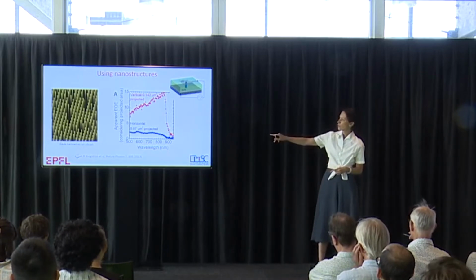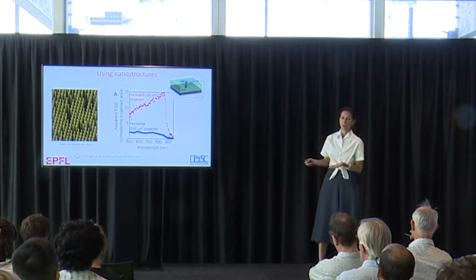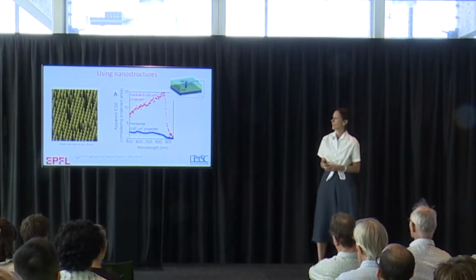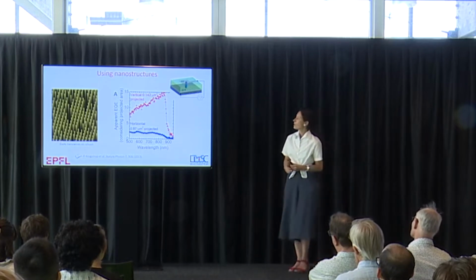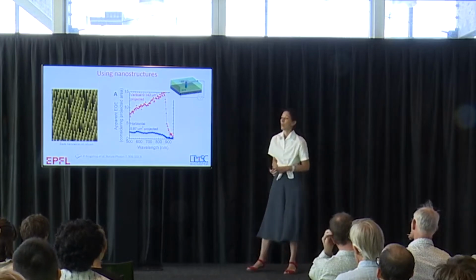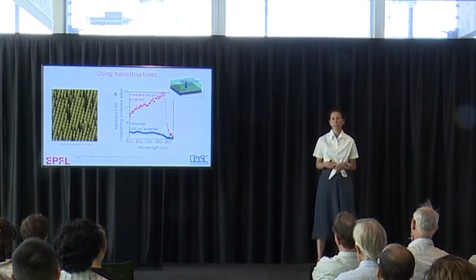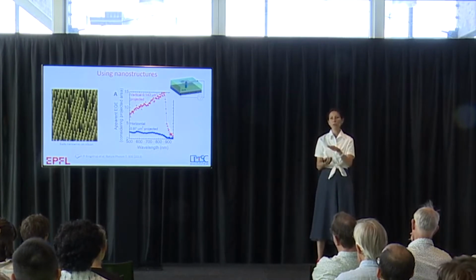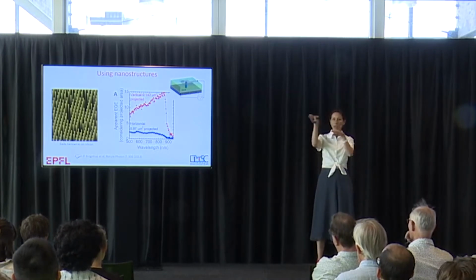As we didn't know how to do this, but we were able to get some wires grown on silicon vertically, we did a single nanowire device with a PN junction. So this is a scheme of the PN junction, and we have a P core of nanowire and an N shell, and we contacted the core through the substrate, the highly doped substrate, and the shell with a transparent contact on top.